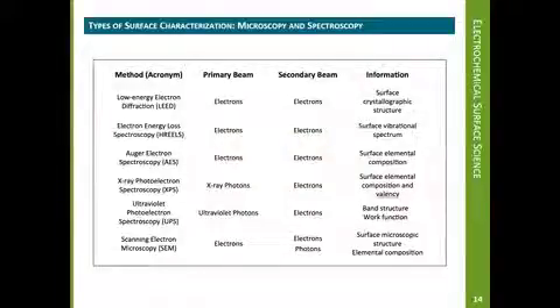To uncover the dependence of catalytic function on structure and composition, our analysis is restricted to the surface and near-surface region by employing electrons and photons of low energy. The particles used exhibit short inelastic mean-free paths in their interaction with solids, and as a result do not penetrate into the bulk. A short list of the techniques which we employ shows that we can gather complementary information regarding the long-range surface crystallinity, surface add-atom bonding, surface elemental composition, atomic valency, fundamental physical properties, and microscopic structure.